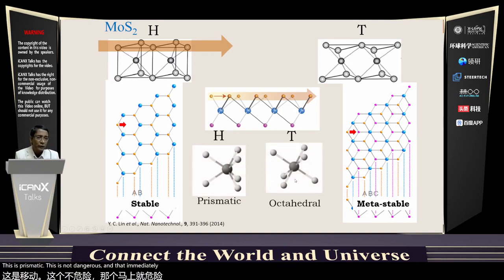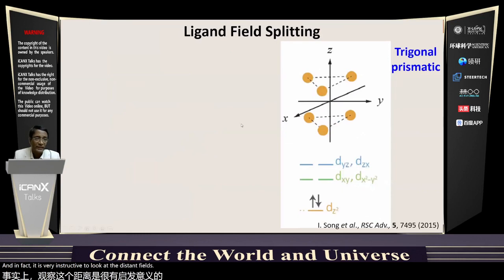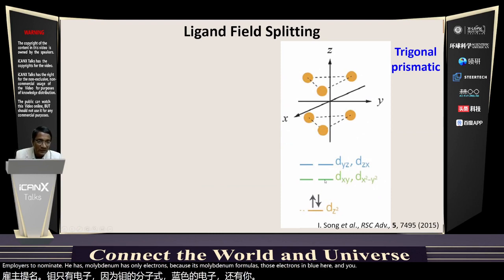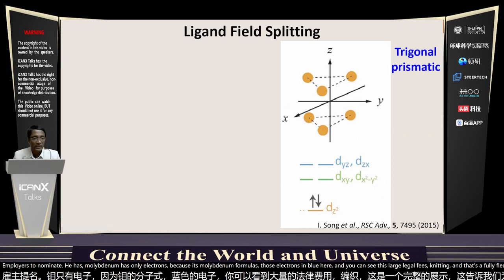And that immediately tells you that the crystal field splitting or the ligand field splitting, because the local coordination is very different, must change drastically. And in fact, it is very instructive to look at the crystal field effect here. So if you take the crystal field effect of an MoS6 prismatic structure, then the molybdenum D level will split into a doubly degenerate level, a singly degenerate level that can take 2 electrons, and then there's a doubly degenerate level, another doubly degenerate level. MoS2 nominally, molybdenum has 2 electrons because it's molybdenum 4+. Those 2 electrons will go here, and you can see this large ligand field splitting, and that's a fully filled shell, and that tells you why the H phase is a large band gap insulator.